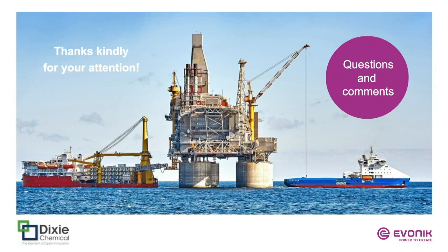Yeah, Vinay, I would agree. In general, you're looking at materials that can react with the anhydride group, open it up to start forming hydroxy groups, which then promote the polymerization to occur. So amines, imidazoles, things like that that have been used historically as epoxy curatives or accelerators, can be used with both dianhydride and monoanhydride systems.